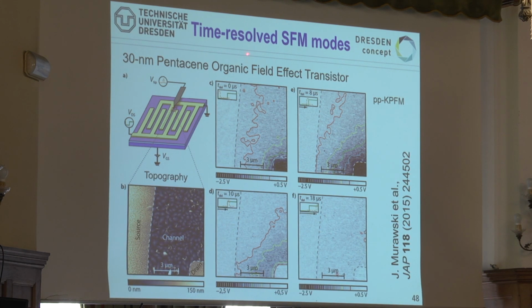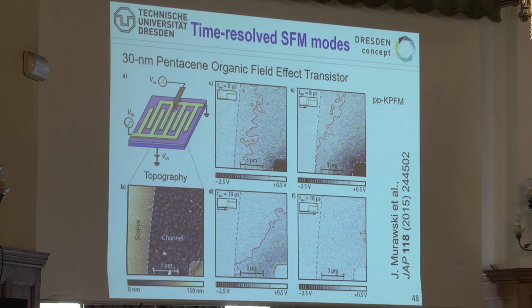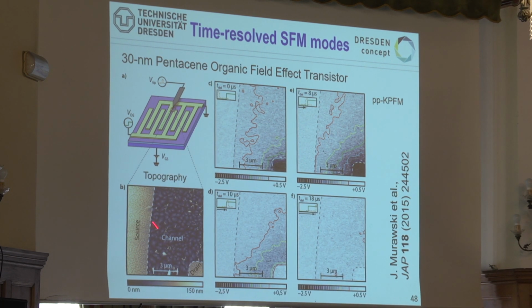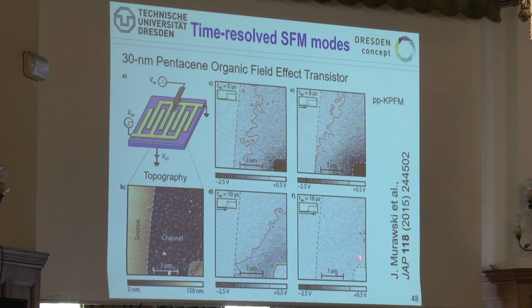And you see nicely one of the wavefronts here, basically it's stuck here. And it's not a straight line of an equipotential line, but it's meandering, simply because we have a structured sample. So all these grains have a little bit different surface potentials, and that's why the potential walls that we have here, which are reflecting the charge density, meander. Let's increase the time. You're going to make stroboscopic images, bang, bang, bang, and you see 8 microseconds, 10 microseconds, the whole wave is gone.